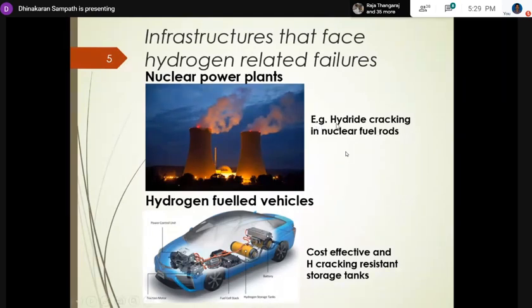Other infrastructures, such as nuclear power plants, also have several of these failure mechanisms. One example is hydride cracking, which is also because of hydrogen getting into the metal. In nuclear fuel rods, they use zirconium alloy, which has a hexagonal close packed crystal, and that alloy forms hydrides with hydrogen. That is a brittle phase, and it starts to crack, which is very, very dangerous. We don't want that, so people work on zirconium alloy to prevent any failure. And as I mentioned about hydrogen fueled vehicles, they are an emerging research area. They are looking for alternatives to stainless steel, which is at the moment resistant enough to postpone fracture.